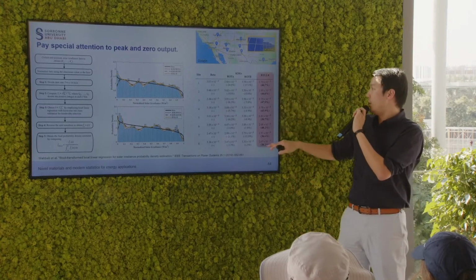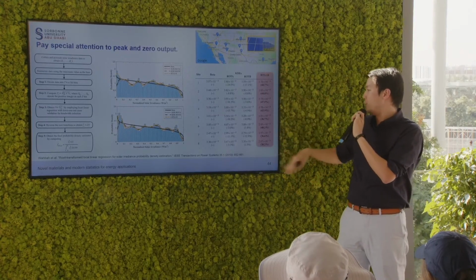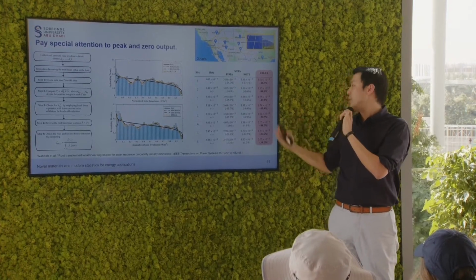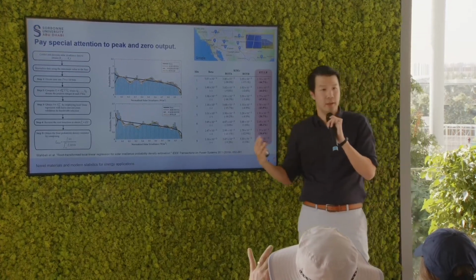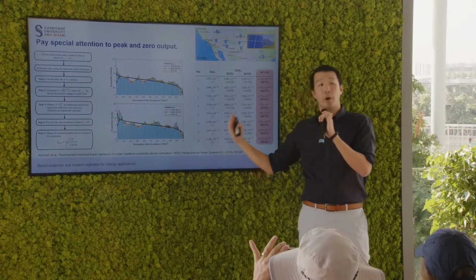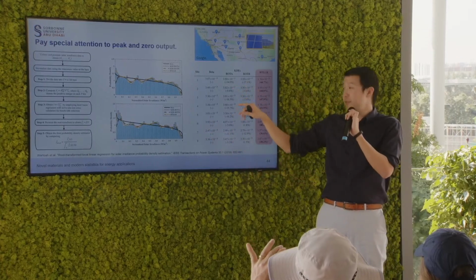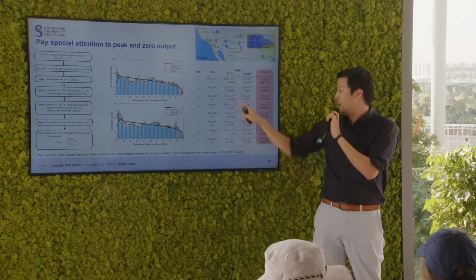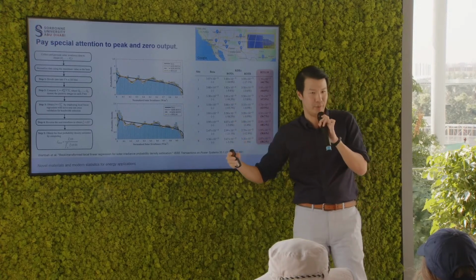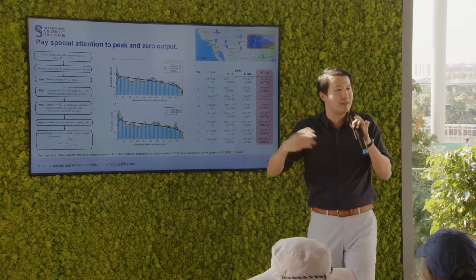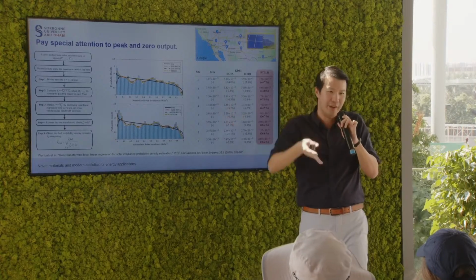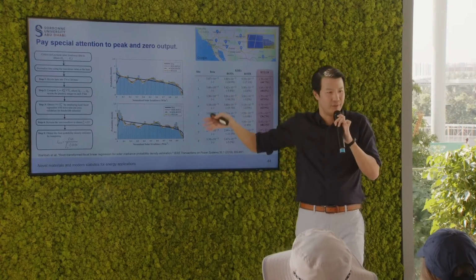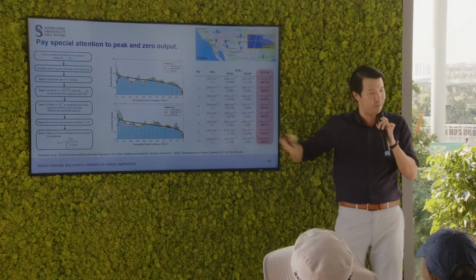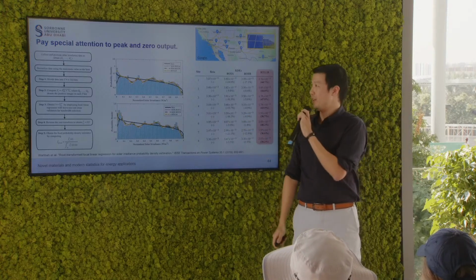So in this situation, our proposed method was able to decrease the error by 30–40% compared to the beta distribution, where even the KDE from the previous slide was actually doing about 10–20% worse than the beta distribution. So it's not just a completely simple story of use one hammer for wind, and then use it for all the other problems that you might have. You have to adapt your methods for the applications.